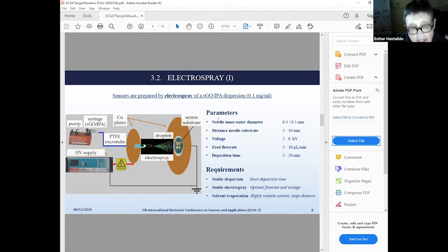And we decided to optimize the process parameters of the electrospray in order to fulfill 3 major requirements. The first one is that the dispersion, because we are not using here surfactants or dispersants to ensure the long-term stability of the dispersion, because we don't want to affect the sensing performance of the base material, which is the reduced graphene oxide. So in this first work, we have not used this surfactant. And so the dispersion must remain stable during the time it takes to prepare the sensors, which in our experiments varied between 5 and 20 minutes. Secondly, the electrospray operation mode should be stable as well. So this is attained by optimal tuning of the dispersion feed rate and also the applied voltage.